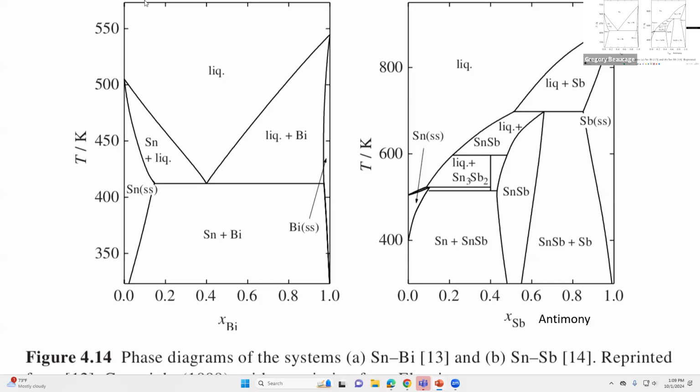That's the delta H of melting for whatever this is. And the slope of this thing over here gives you the delta H of melting for pure bismuth. And delta H is what you need to construct the whole phase diagram also. If you want to reconstruct this phase diagram under an ideal condition, all you need is the delta H and the freezing point, which you have.